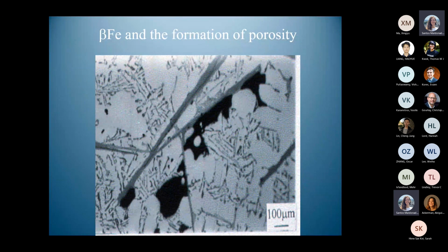And here's another instance where the beta iron has grown long crystals, and here's one. But here, the beta iron has only grown on one half of the bifilm and straightened that half out. But on the other side, so there's the beta particle on one side, but on the other side, nothing happened to grow. Nothing arrived there to nucleate. And so that was free as an oxide film to wander off and would do whatever it wanted. And of course, as, for instance, the hydrogen increases in these regions, the hydrogen will blow it off, or if there's shrinkage here, it'll actually suck it away.